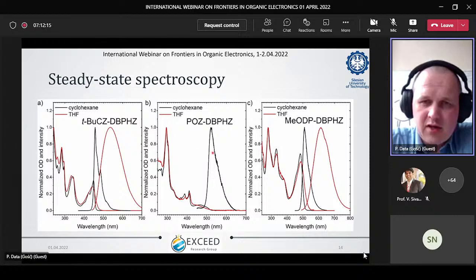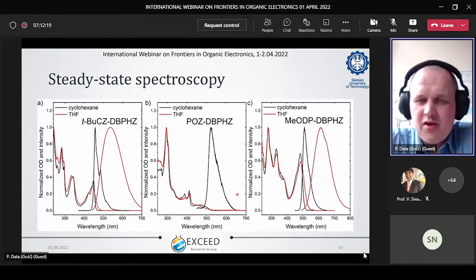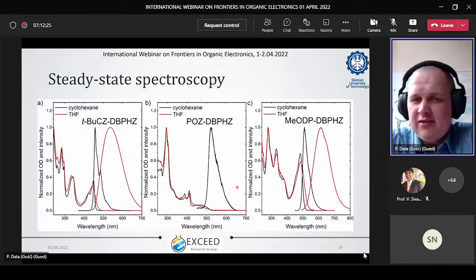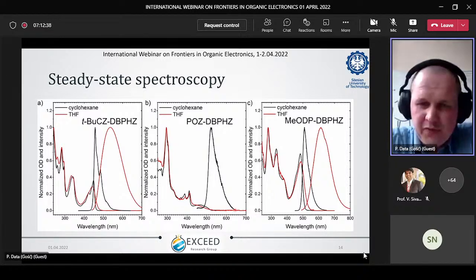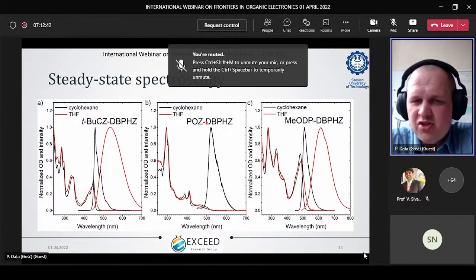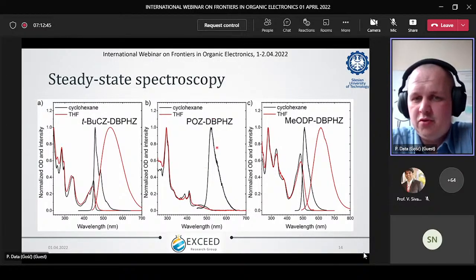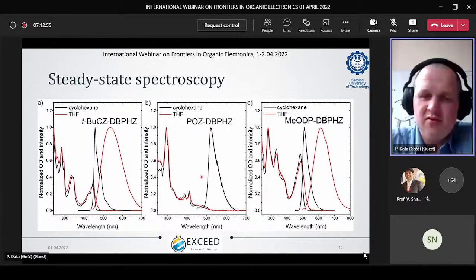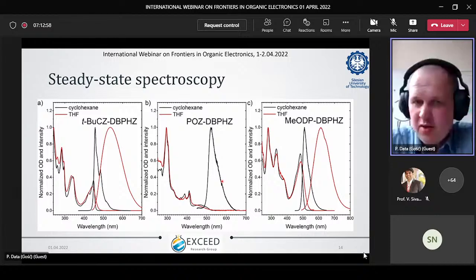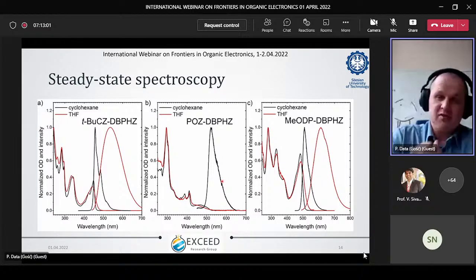In some cases, if you look at the middle one, we don't have emission in THF, tetrahydrofuran, at all. What is important for you to know, it doesn't mean that we don't have a charge transfer process or there is no charge transfer in the molecule. Sometimes the emission disappears mostly because the charge transfer process is so strong that a very small amount of oxygen simply quenches your whole emission. If you have emission in THF which is almost exactly like the one in cyclohexane or in non-polar solvent, that means you don't have CT emission at all, or charge transfer process, in your molecule.